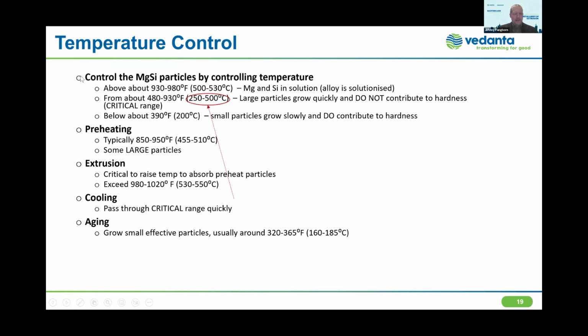I won't read all this, but again, there's this critical temperature range, 250 to 500 C. For preheating, we'll just want to highlight 455 to 510 C is pretty typical for 6,000 alloys at least. We will start to grow some large particles, but in the extrusion process, if we're keeping our extrusion exit temperature high, we'll be able to absorb those particles. Cooling needs to be quick enough to absorb. I don't have it on here, but for 6063, if we come through that range in 4 to 5 minutes, that would generally be perfectly acceptable. For a 6061, for example, probably at most 2 minutes, depending on the wall thicknesses and so forth. And then aging, typical aging temperatures, there can be exceptions to this as well, but 160 to 185 C.